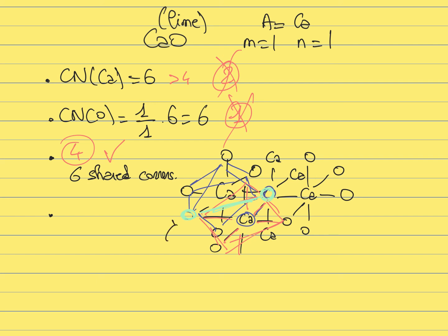So that would be an example where you cannot avoid the formation of edge sharing units. And those edge sharing units are forbidden by the Zachariasen rule. It doesn't satisfy the third Zachariasen rule. So in this case, since you cannot draw the structure without having some edge sharing unit, the third Zachariasen rule would not be satisfied.